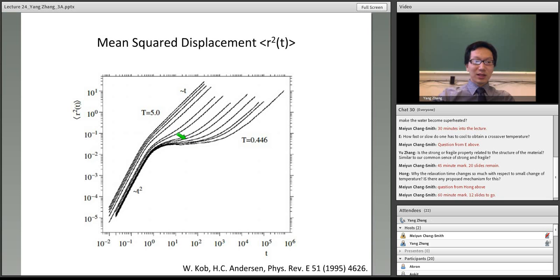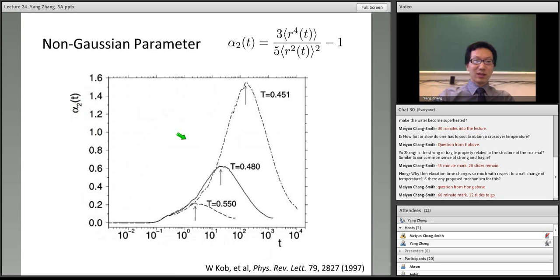And the next quantity that is often used to quantify the dynamic heterogeneity is the non-Gaussian parameter, which is basically the next order term of the mean square displacement. If the liquid is not heterogeneous, if the diffusion is just pure Debye-like exponential, then the non-Gaussian parameter should be 0. But in supercooled liquid, as the temperature is cooled, you can see that the system becomes more and more non-Gaussian. So the peak of this alpha 2 can be used to quantify the size of the dynamic heterogeneity as the temperature is lowered.